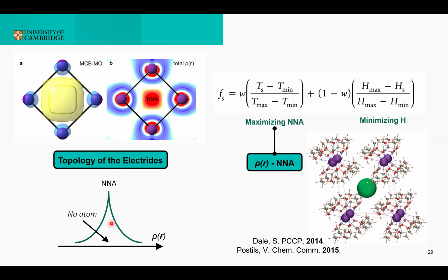In fact, atoms are basically nuclear attractors that attract the electron density and they correspond to a maximum of the electron density when we try to map this quantity. And therefore, the presence of a maximum without a nucleus is quite uncommon, as you can imagine. Since non-nuclear attractors are then characteristic of the electride state, we can imagine to use them in our crystal structure prediction to improve the search of this type of materials. Therefore, what I did was to use the amount of the electron density that one would find at a non-nuclear attractor, which is basically a quantification of the concentration or the amount of electron density, so the level of electrideness of a system, as an objective in our crystal structure prediction.